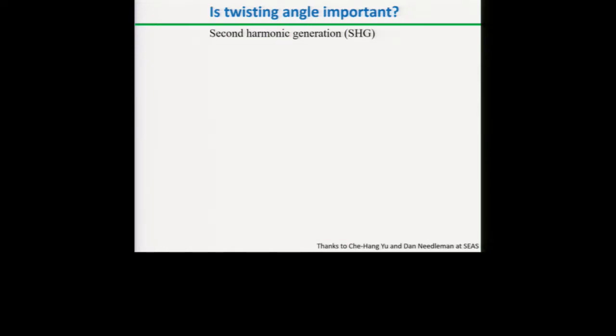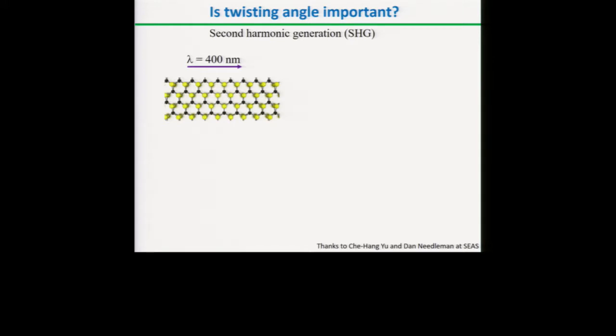So that's why I have this question: is twisting angle important? In order to find out the alignment, we have to align them in momentum space as well. What we do is we use a second harmonic generation microscope. It's all in SEAS, in the biophysics department. We use a laser at around 400 nanometers, polarized in one direction.